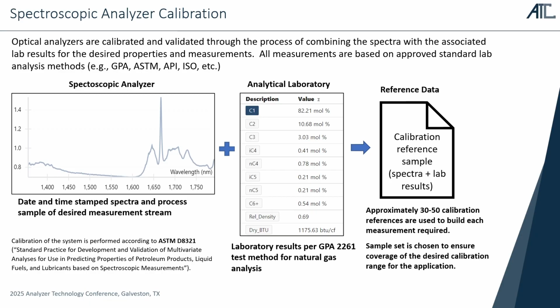So how we calibrate spectroscopic analyzers, both Raman and NIR analyzers, is with chemometric modeling, following ASTM D8321. And how we do that is you take a spectrum of your sample with your spectroscopic analyzer. You collect that sample in the appropriate sample container, and you take that to a lab. You have that measured in the lab with a primary method. In this example, we're using GPA 2261 for the composition of a gas. And that provides you a laboratory value. So we have a primary method laboratory value and a spectrum of the sample.